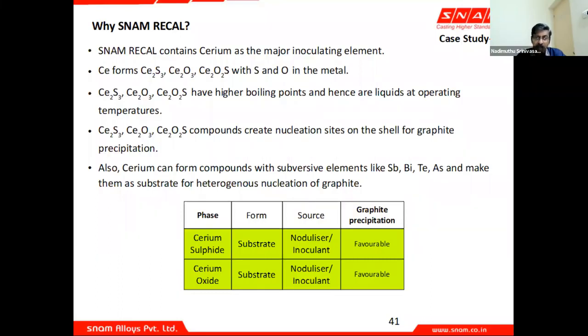They have a higher boiling point, and they are liquids at operating temperature. And when solidified, they create that substrate on the shell for the graphite precipitation. Cerium can also form compounds with subversive elements like Sb, Te, As, and all this. And these substrates also have the structure so that they facilitate the graphite precipitation.